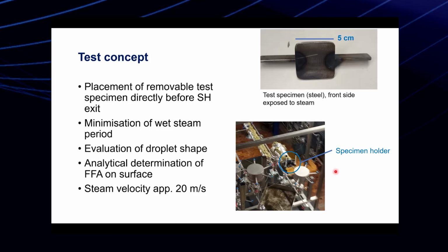We try as much as possible to minimize the wet steam period because we want to make sure that it is dry steam as much as possible. This is what we want to confirm. After that, we do evaluations on the droplet shapes and analytical determination of FFA on the surface. So this is what we are doing.